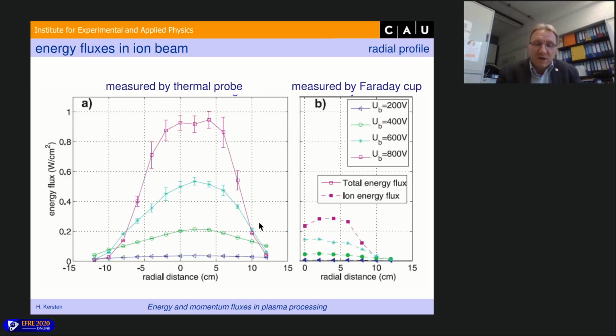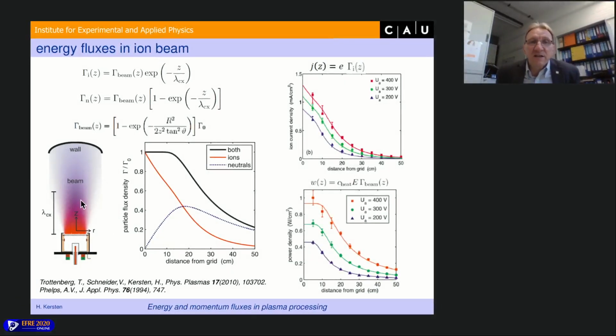And then if you would assume that only ions are coming from the source, then you can just calculate the energy influx by multiplying the energy, which is given by the beam voltage, and the flux density. The flux density can be measured by a Faraday cup, and the energy we know from the beam voltage. And if we multiply this, we get these radial profiles. And these radial profiles are smaller by a factor of 2 or 3 than those measured by our thermal probe. And why? This is simply because in our chamber, the background pressure is not very low. There is a background pressure of a Pascal or something like that.